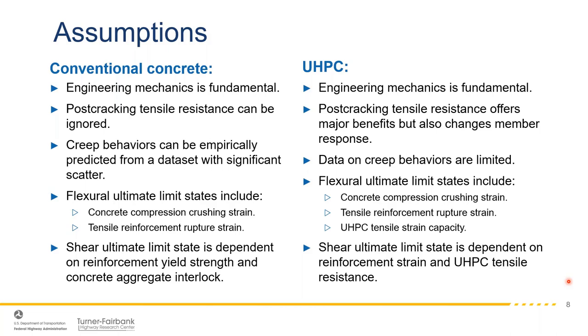So there's another limit state that needs to be considered, and we need to look at when we get to each limit. And I'll just give you a warning. Sometimes with UHPC, we're going to reach the UHPC limit first. We're going to get to what's called localization, which is when the fibers start to pull out of the matrix. So you stretch the UHPC, the fibers pull out, and you're going to lose resistance. And that's an important limit state you need to consider.